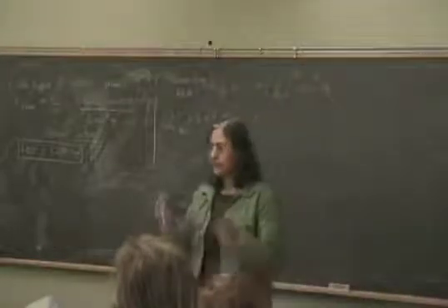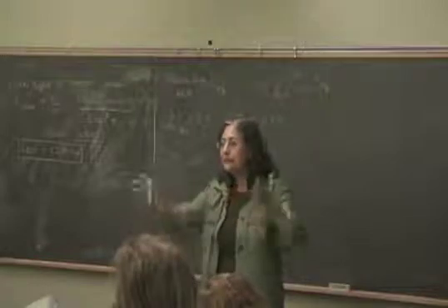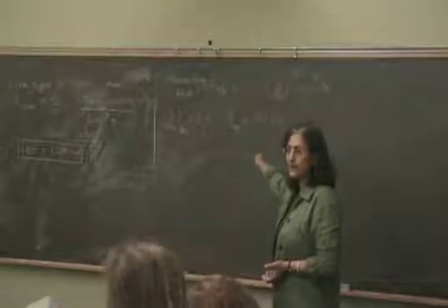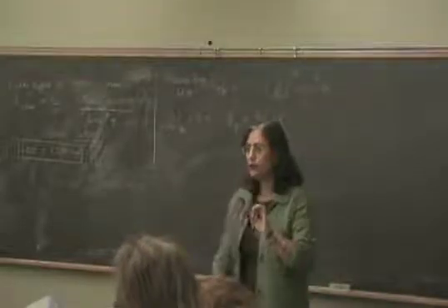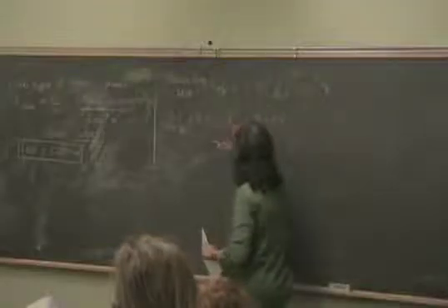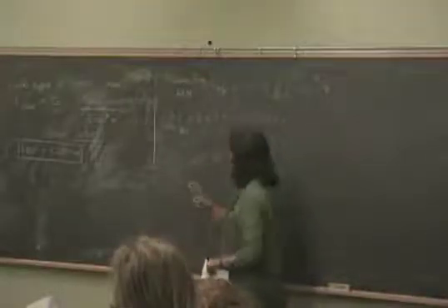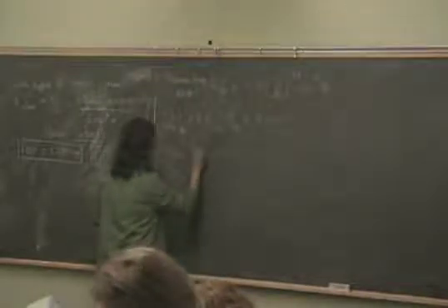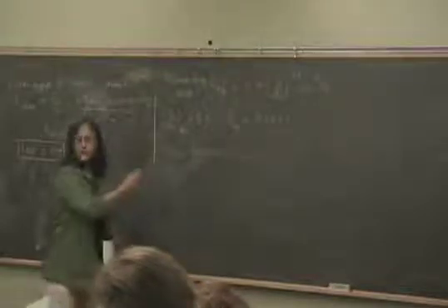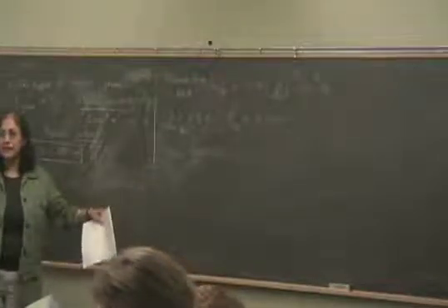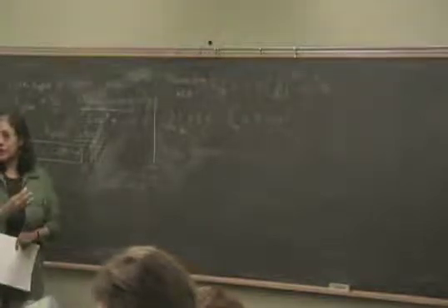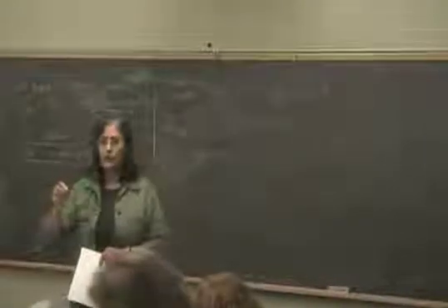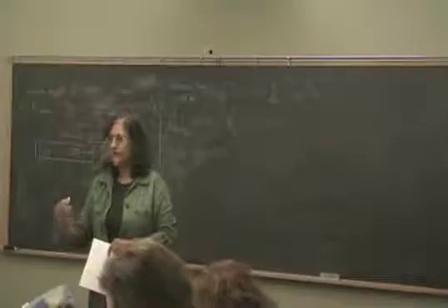Except the differences are a couple of things I'm going to bring up. If it was an infinite slab of gold, it would absorb at that frequency. Absolutely. Now what we have to bring in are a couple of steps between this and the actual experiment. One is that it is a gold sphere. So we want to understand what making gold from a big bulk into a sphere does to the plasma oscillation. That's one step. And the second step is that the gold nanoparticles are embedded in a dielectric.